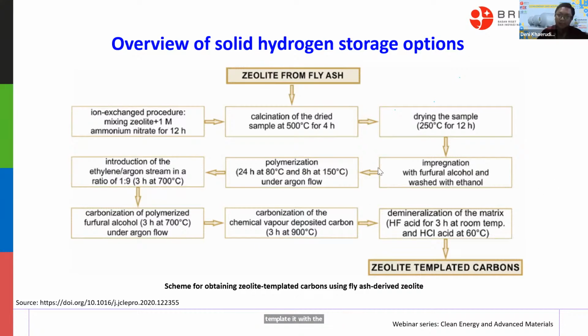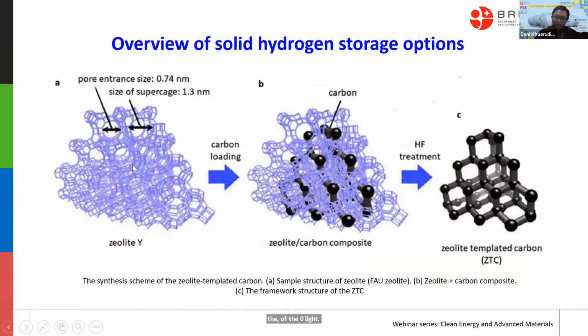This is just a general step. If you want to utilize the fly ash as the resource of the zeolite, then after that, the zeolite is templated into carbon as the sorbent of hydrogen. Okay, so this is the schematic illustration: the zeolite Y, then the zeolite and carbon composite, and when it is templated, we call it ZTC, zeolite templated carbon. So this material has high performance compared with the pure zeolite.